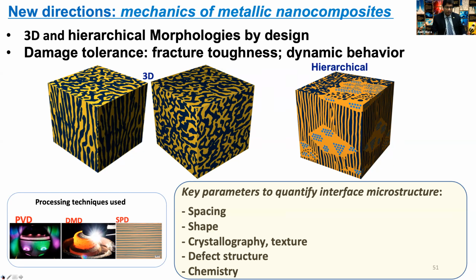And I showed in that plot that with compression, you get slightly higher because with tension, sometimes you get fracture before yield. But your question is very good, that you have to know the yield strength of the microstructure that we are seeing on this slide. You have to know the yield strength of this microstructure to be able to know the fracture toughness once you measure the crack opening displacement from those tests.